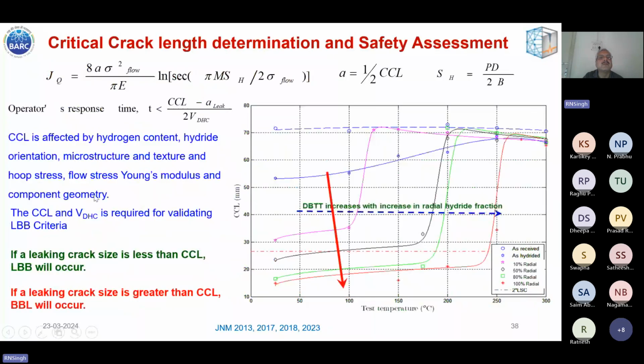So here it is shown. This is the JQ parameter obtained experimentally, and SH is the hoop stress, sigma flow is the flow stress of the material, and the Folias factor M is a relationship between tube geometry and crack size and all. And here the operator response time has to be less than the time required for a leak size crack to exceed the critical crack length. In the denominator, you have twice the DHC velocity, because the crack can go axially in both directions.